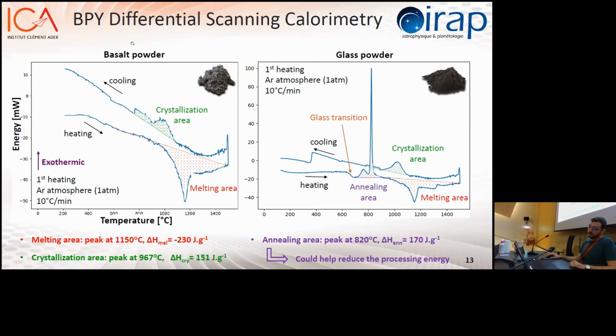For example, if you take the original basalt powder, when you heat, you have a huge melting area, and then you have the corresponding crystallization area when cooling down. In the same way, if you look at the glass powder, you have two phenomena appearing. First, the glass transition temperature, which is the point at which glass enters a viscous state and gains some mobility. After that, you have the annealing area, in which glass has enough energy to actually recrystallize into a new phase. This annealing area is exothermic, so it could help us reduce a little bit the energy of the process. And it gives us precious information about the kind of material we can get at the end of the SLM process.